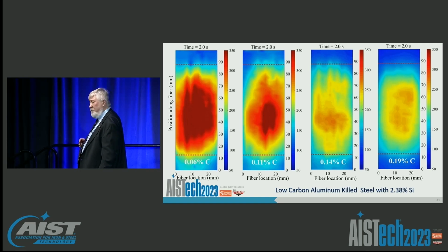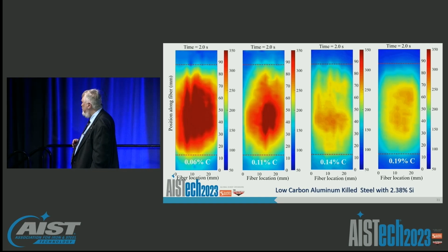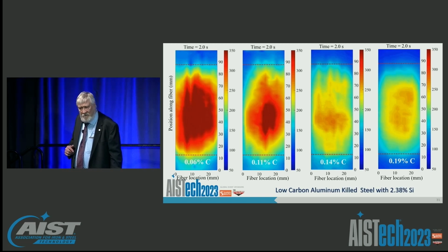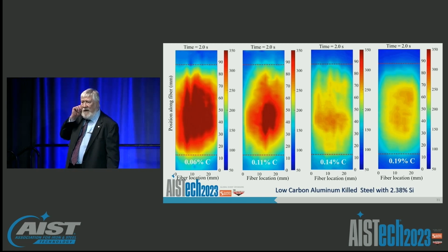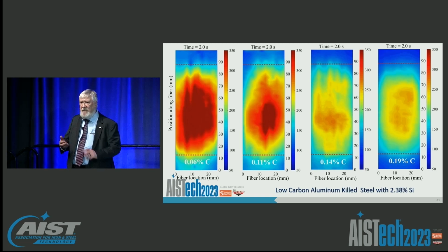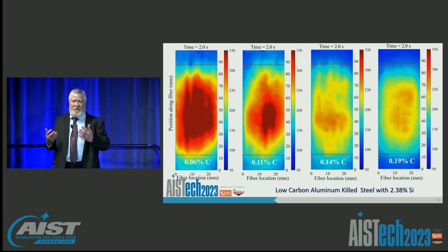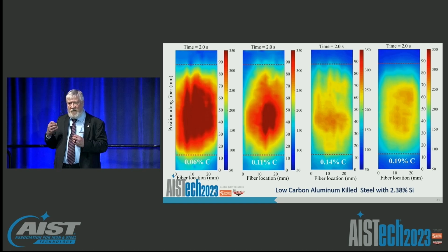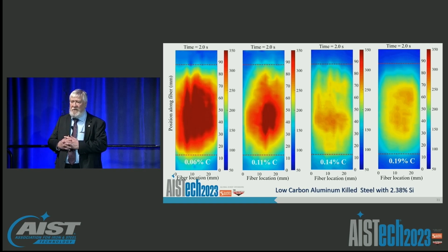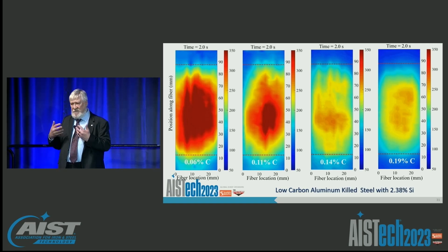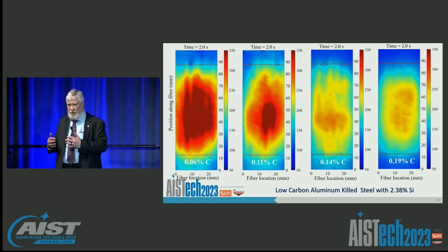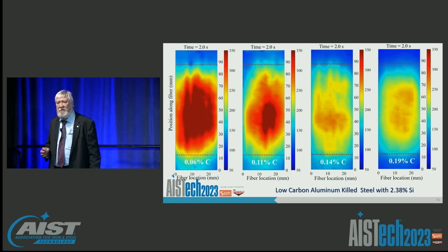But is the conclusion that the non-uniformities in the formation of the bulging shell in peritectic grades is because of a non-uniformity in heat flow? No, I think it's directly related to the nature of the peritectic solidification. In fact, most people would say that it's the abrupt density change from delta ferrite to austenite that induces strains that actually cannot be withstood by the shell and create that buckling. Thank you very much. You're welcome.